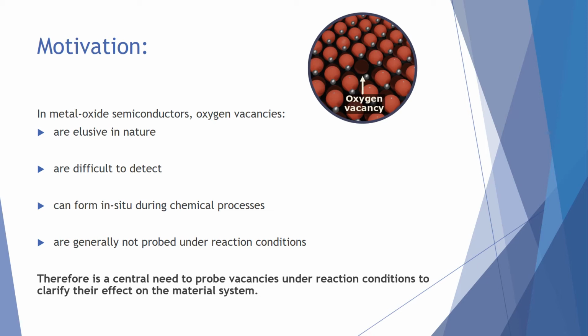On top of that, vacancies are not generally probed under reactive conditions. They're very difficult to probe and therefore often done through scanning techniques under ultra-high vacuum, very low temperatures, or with single crystals. So, in conditions of samples that are very far from ideal reactive conditions. And therefore, there's a central need to probe vacancies under reactive conditions to clarify their effect on the material system and how they affect different mechanisms.